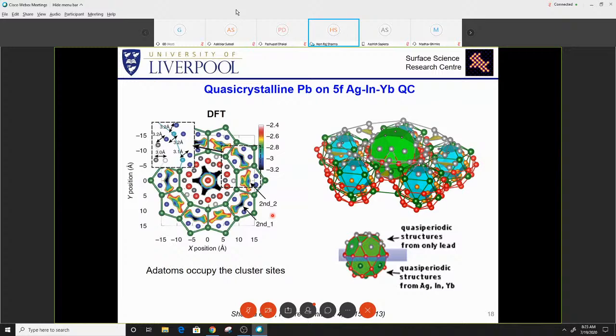As I said, these clusters are used to explain the structure of the bulk. When we form a surface, basically, the surface bisects the cluster center. You have like a half cluster, with that kind of back and side. So if you deposit the lead or the element, it simply sits on the back and side. So that basically mirrors the underlying half cluster. It's a simple picture, but the real structure is complex.